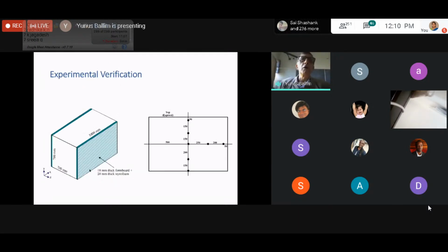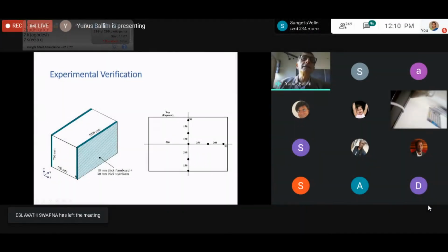We cast a block of concrete in the lab, and we used only half a cubic meter of concrete. I say only, that's still sort of 1.2 tons of concrete. But we arranged it so that we had 1,000 millimeters in this direction, 1 meter, 700 millimeters in this direction, 700 millimeters in this direction. Okay, and then we heavily insulated these 2 surfaces.